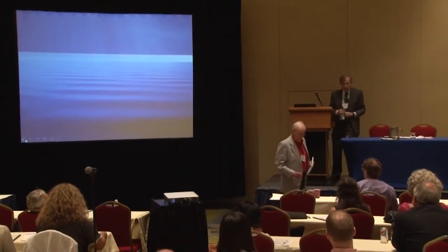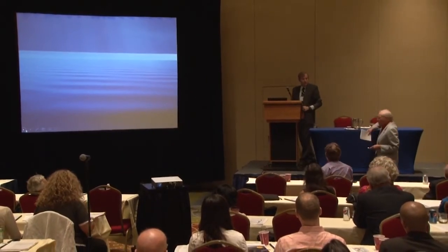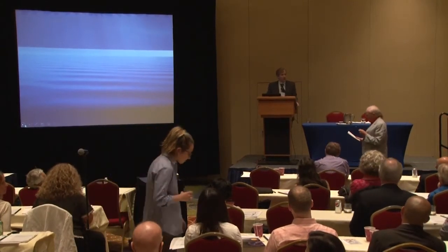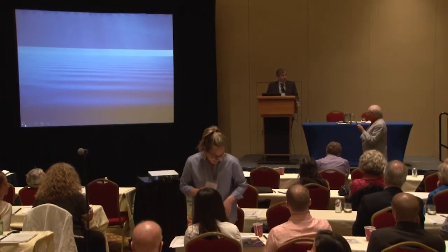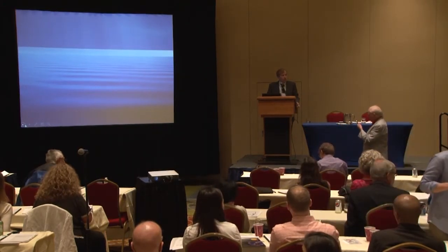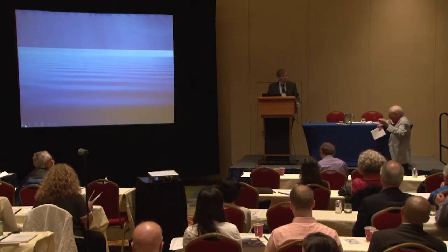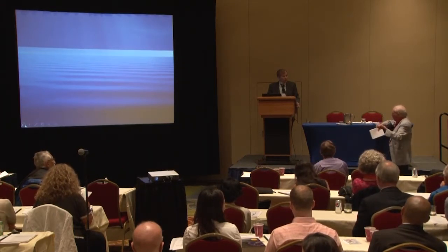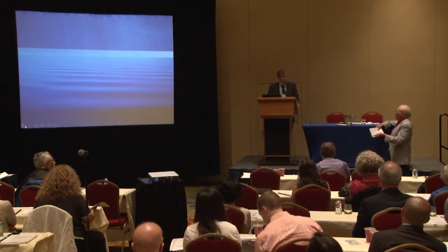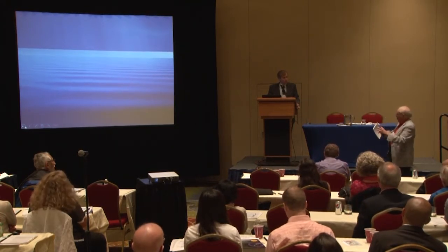Thanks, Brian. I'd like to use my chairman's prerogative to ask a couple myself. One important distinction, I think, is between devitrification and recrystallization. In devitrification, you're seeing the full effect, where you're getting the full evolution of heat and liquid diffusion. Whereas recrystallization is probably almost infinitesimally small differences in enthalpy between small crystals and large.